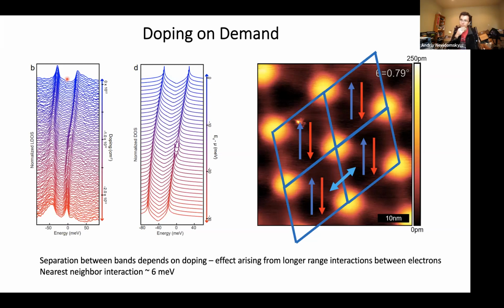Sorry, so let's say we are not precisely at the magic angle, right? Even within MacDonald's calculation, you have 2 Van Hoves, and the spacing between those Van Hoves is very small. In MacDonald's calculation, at the angle where we are, that spacing is going to be much less than 1 millivolt. Now, the experimental finding is that it's not 1 millivolt, it's more like 40 millivolts. Does that make sense? Right.